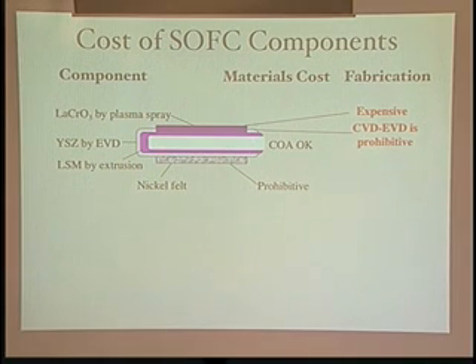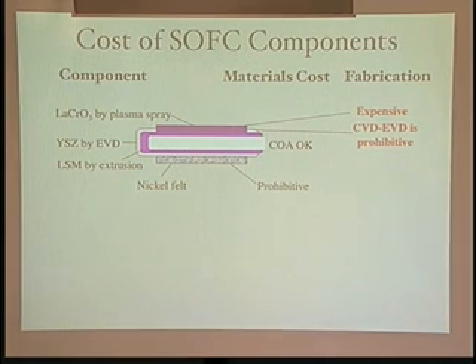And the way they do that is they start with an air electrode, and they do something called CVD-EVD. It's a vapor deposition process. It's really expensive. It's a batch process, and it's tremendously expensive. And even this, what's called an interconnect, is put down by plasma spray. It's fine for thermal barrier coatings for turbines, but again, it's too expensive for fuel cells. So this approach becomes very expensive.